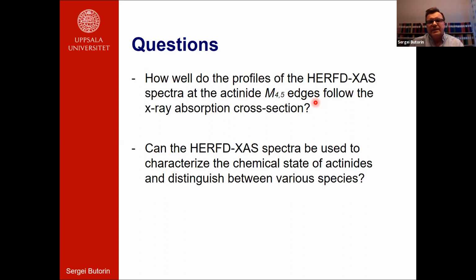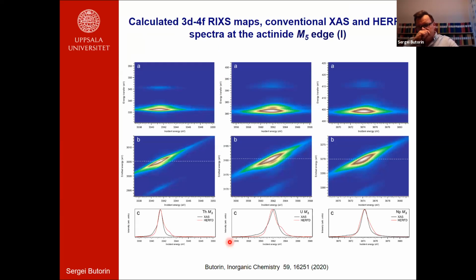But that raises some questions. How well do the profiles of the RIXS spectra at actinide M edges follow the X-ray absorption cross-section? And can the HERFD spectra actually be used to characterize the chemical state of actinides or distinguish between various species? I'll try to address these questions by doing crystal field calculations, to start with, of the 3d4f RIXS maps, conventional XAS and HERFD spectra. Unfortunately, I have to skip the details of the calculations, but they are already published in this paper, so one can take a look there if interested.